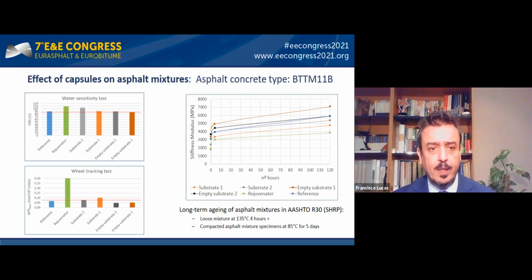Additionally, we have calculated the stiffness modulus to measure the long-term behavior of the mixtures according to the AASHTO R30 method at 135 degrees during 4 hours and 85 degrees during 5 days, resulting in values consistent with the starting hypothesis and showing the proper behavior of rejuvenating agents.